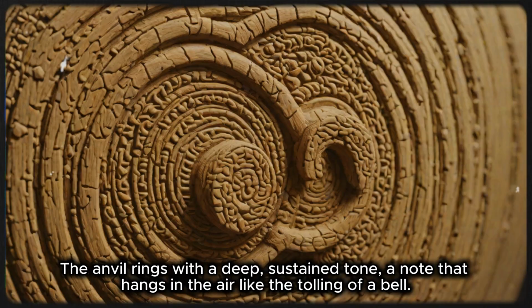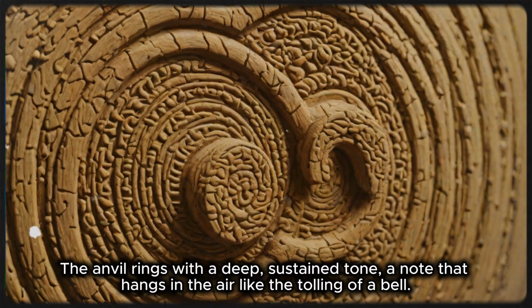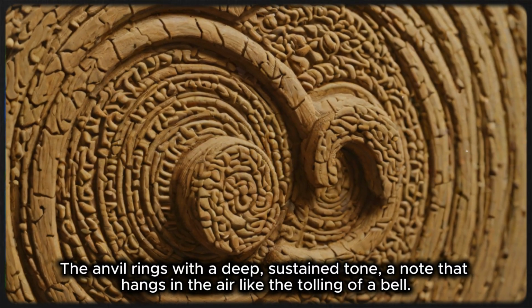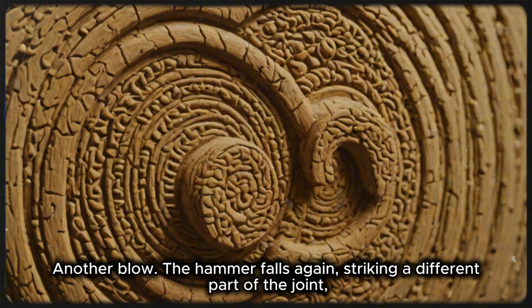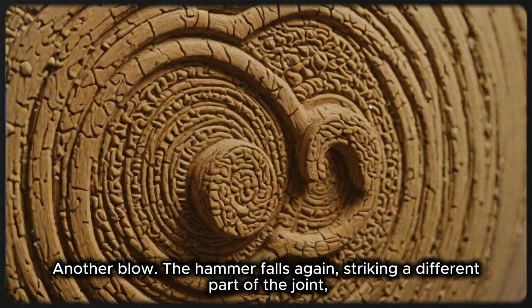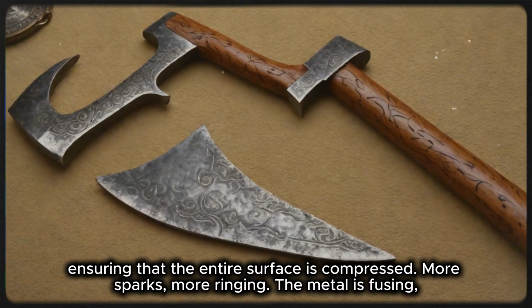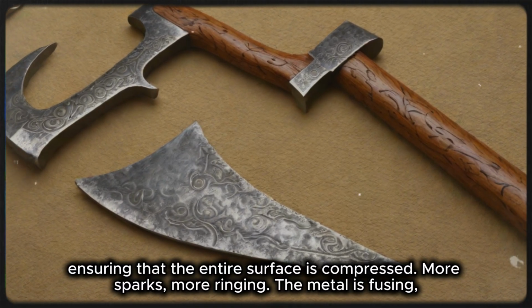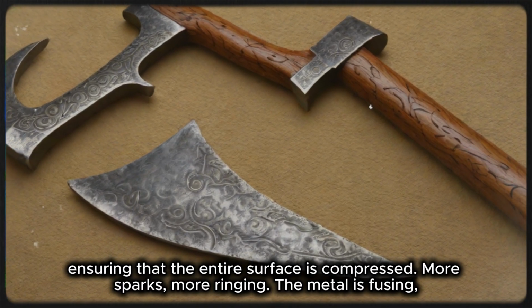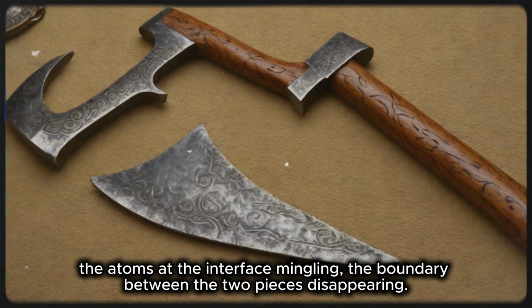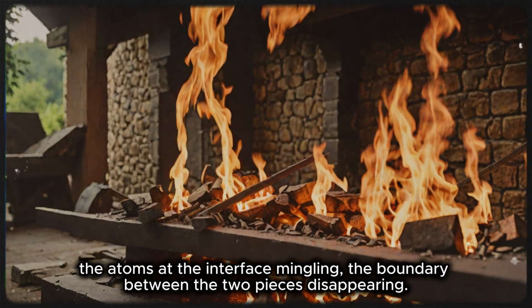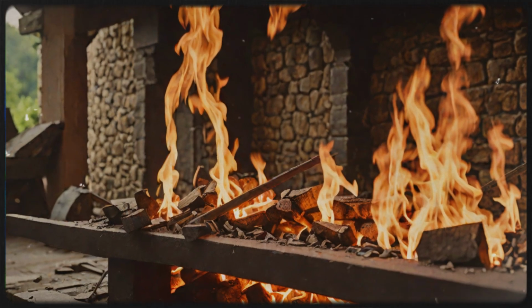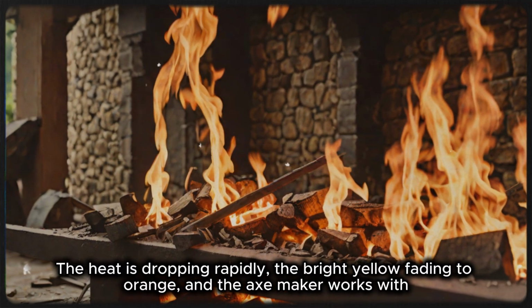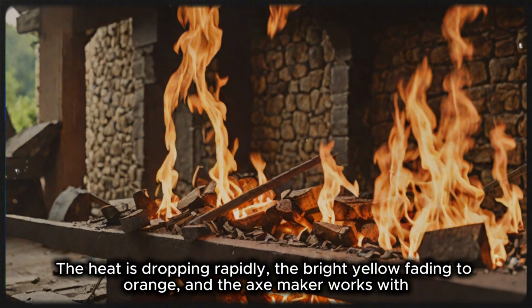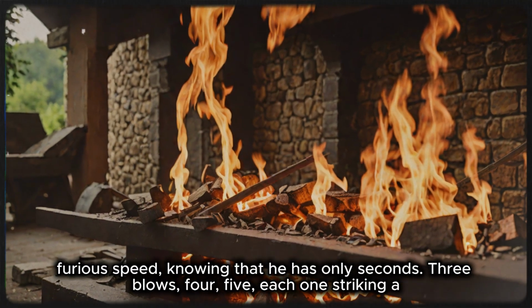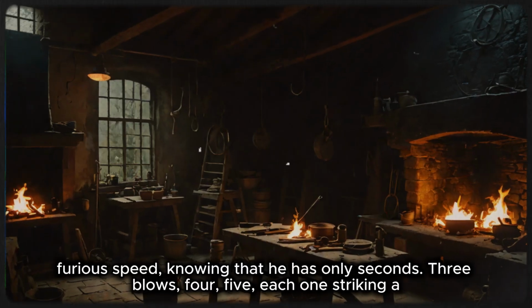The anvil rings with a deep, sustained tone, a note that hangs in the air like the tolling of a bell. Another blow. The hammer falls again, striking a different part of the joint, ensuring that the entire surface is compressed. More sparks, more ringing. The metal is fusing, the atoms at the interface mingling, the boundary between the two pieces disappearing. The heat is dropping rapidly, the bright yellow fading to orange, and the axe maker works with furious speed, knowing that he has only seconds.